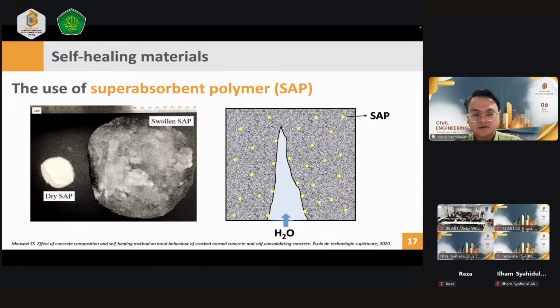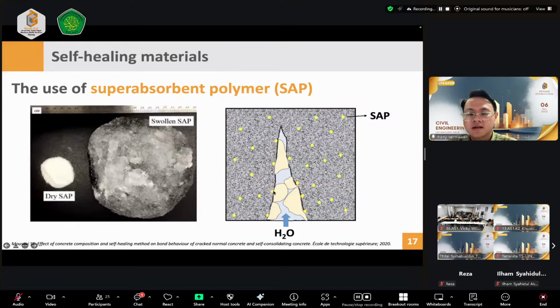So what is the function or what is the objective of using this SAP in the concrete? On the picture on the right hand side, imagine concrete which has been added with the SAP. We have also a crack coming into the material and the water enters the crack. So what's going on? Later this SAP will swell and eventually block the ingress of the water. So we are sure the water will not penetrate rapidly into the tip of the crack.